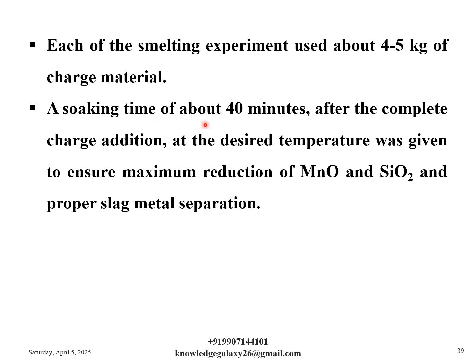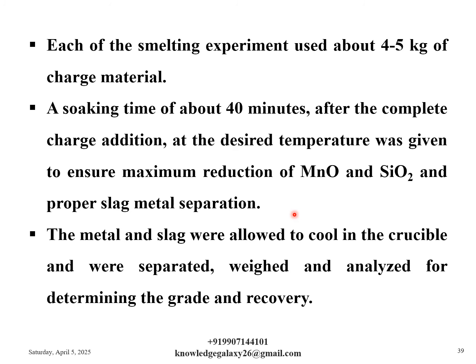A soaking time of about 40 minutes after the complete charge addition at the desired temperature was given to ensure maximum reduction of MnO and SiO2 and proper slag metal separation. Then the metal and slag were allowed to cool in the crucible, and were separated, weighed and analyzed for determining the grade and recovery.